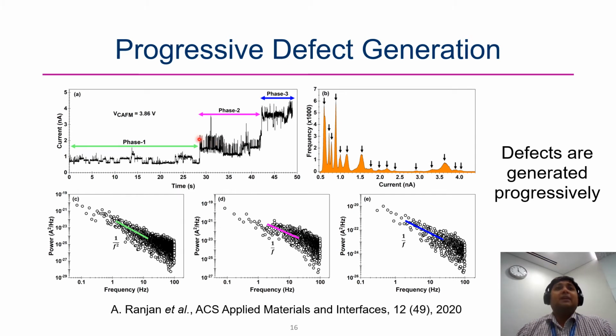This is another example where we see in real time how the defects are being created. You can see that to start with, we have essentially a two-level RTN, but as the time progresses, we can see that there is a sudden jump in the current. It means that we have created a defect, and also the DC levels shift, and we have more RTN levels. If we plot this data in a histogram, we can see that we have at least 16 levels of the current, which tells that we have created at least 4 defects.